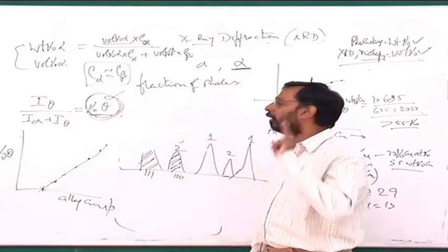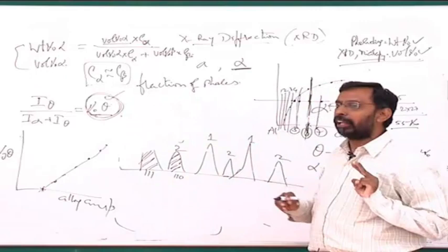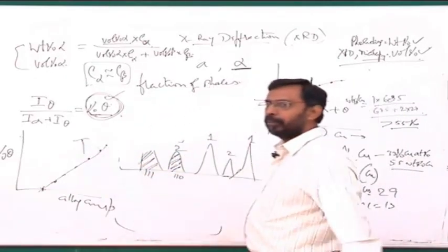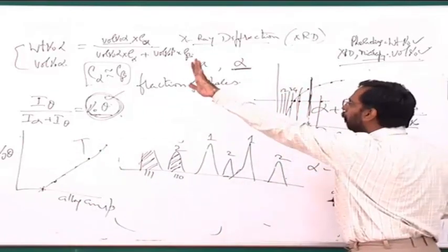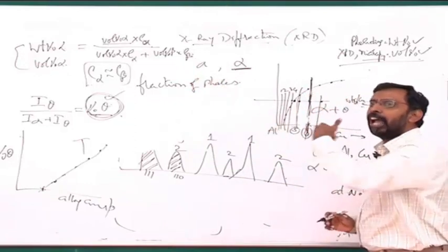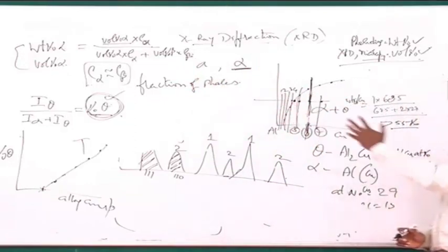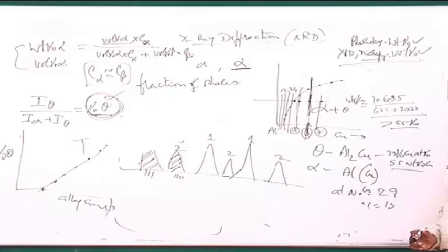So there are two methods of doing the solvus line calculation, and I do this for various temperatures. This is only for one temperature, because I have heated to this temperature and quenched all the alloys. And I will now not bother about alloys containing only one single phase. I will throw them away. I will only consider alloys which are showing the two-phase mixture.